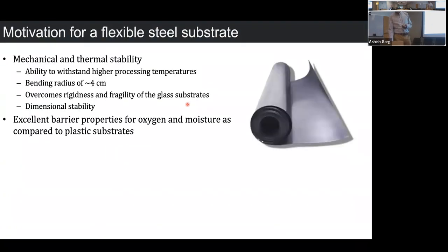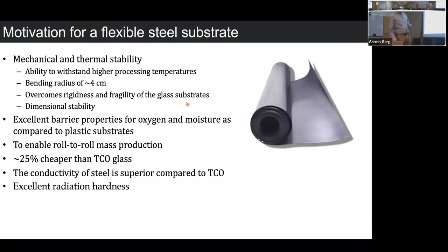So why a steel substrate? I've given you some heads up earlier, but not only do they want to commercialize this as part of a solar cell integrated steel roof, there is apparently a significant cost reduction when you use steel as a substrate, which is about 25% cheaper as compared to TCO coated glass. And TCO uses indium, which is not a very prevalent kind of metal. So as a result, there is an interest in making these solar cells on a steel substrate. Other than that, there is a possibility of using steel as an electrode itself because it's conducting. And then steel also has excellent radiation hardness. So there are certain advantages to using steel, in addition to excellent barrier properties for oxygen and moisture.